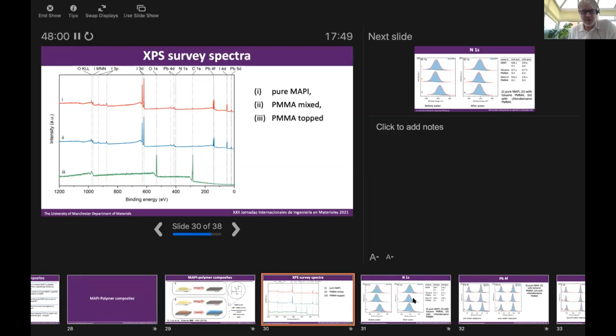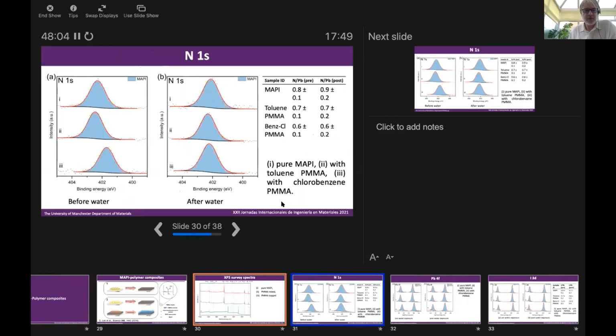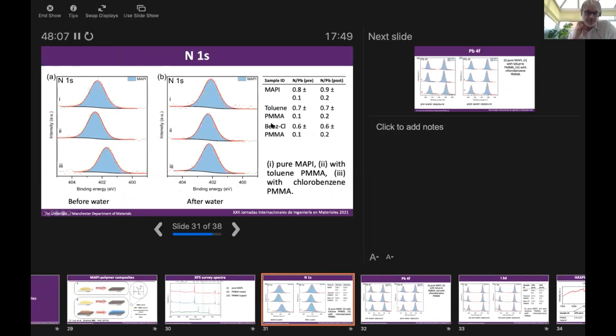We did do some normal XPS of the composites. We measure the material before and after water, and actually we find that the nitrogen doesn't change appreciably for any of the blends. So PMMA, even just being mixed with the MAPI, appears to offer some protection to the MAPI.